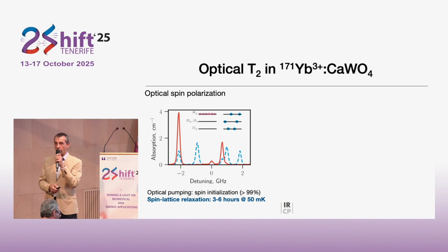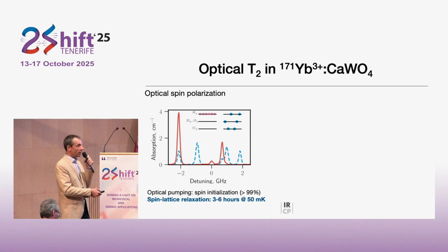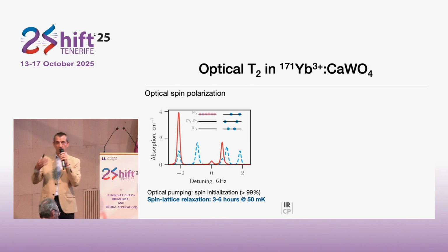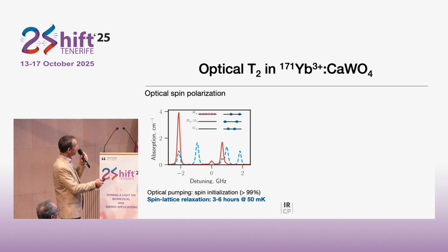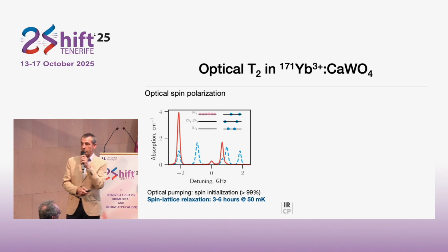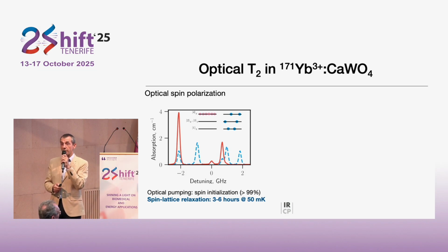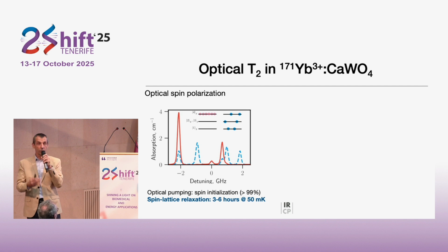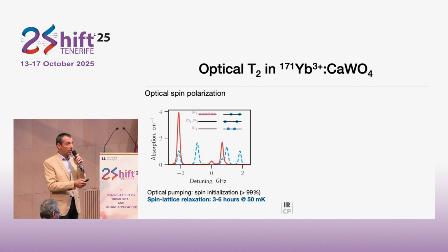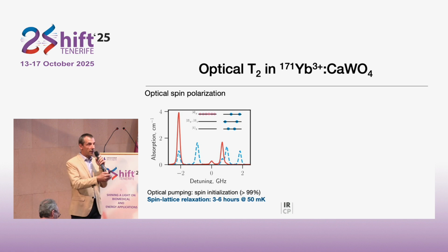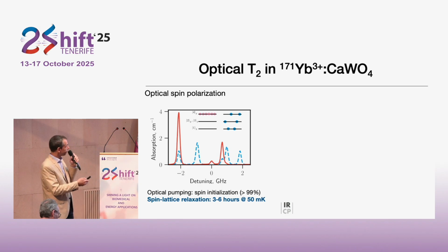Another very interesting feature is that this situation where we have this strong spin polarization is going to last for a very long time. Of course, again, we are at extremely low temperatures, 50 milliK, but in this case, we can observe that the spin relaxation, so the thermalization, if you want, of this situation towards this situation will take a few hours, 3 to 6 hours at this temperature. And this is very nice because you don't need to refresh the polarization very often. You can simply do it once, and then this will last for a long time.